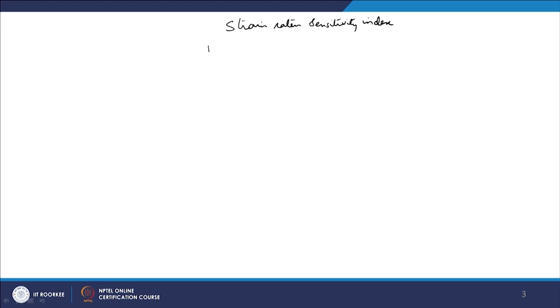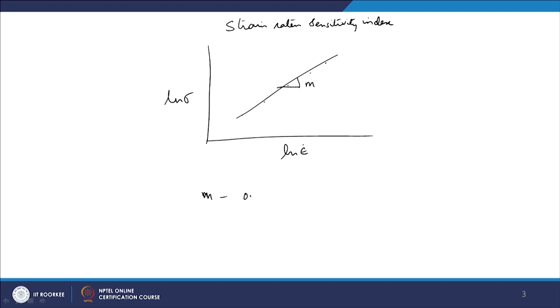So, if I plot ln of sigma versus ln of epsilon dot, I should get some points like this. If I fit a linear curve here, the slope should give me the strain rate sensitivity of the material. And the strain rate sensitivity, for industrial hot deformation processes like rolling, extrusion and all that, the value may be somewhere between 0.1 to 0.2, for hot deformation in industry.